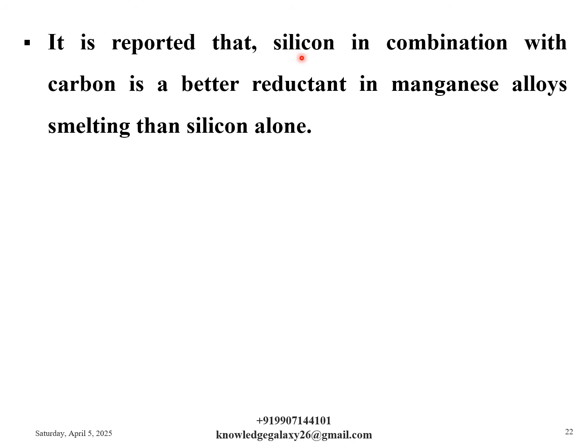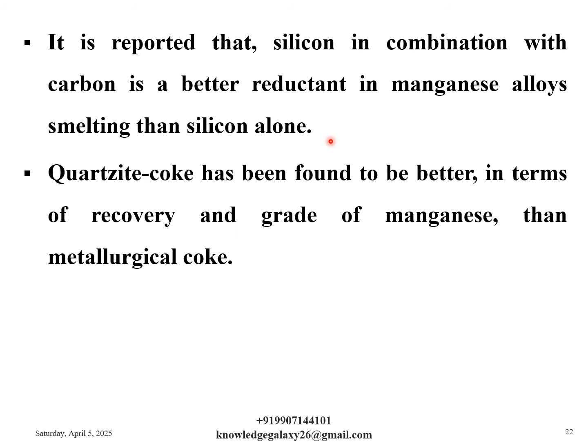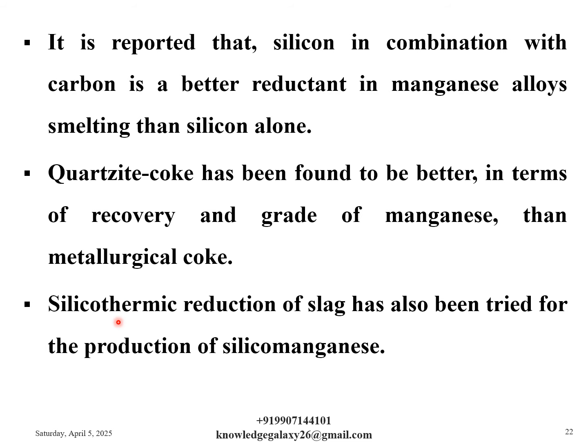It is reported that silicon in combination with carbon is a better reductant in manganese alloys smelting than silicon alone. Quartzite coke has been found to be better in terms of recovery and grade of manganese than metallurgical coke. Silicothermic reduction of slag has also been tried for the production of silicomanganese.